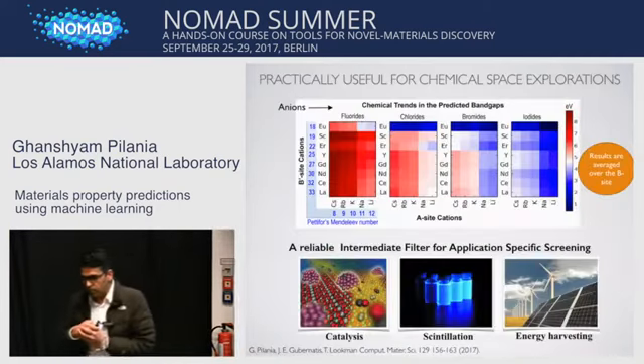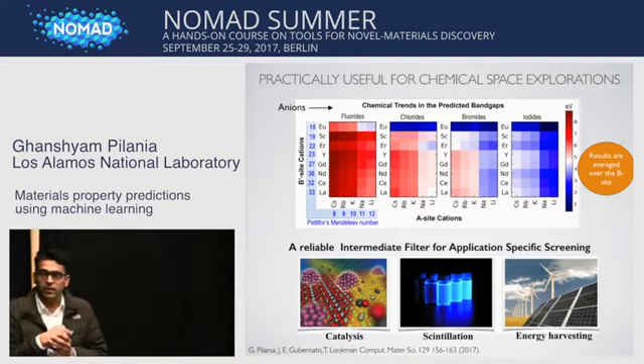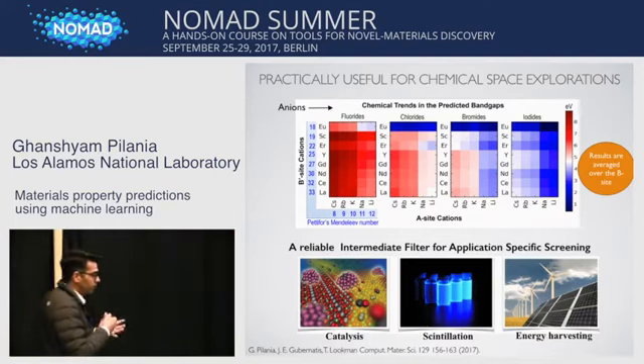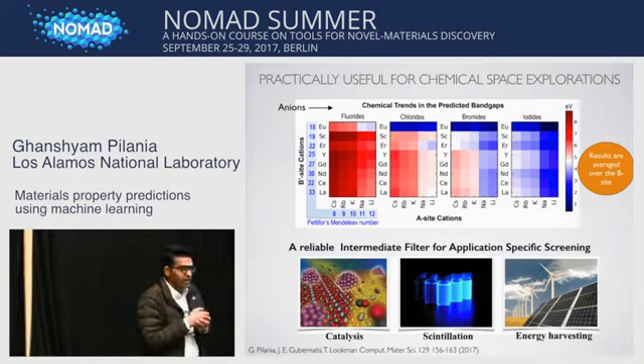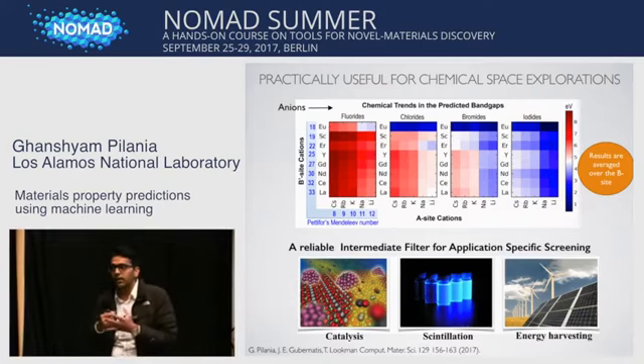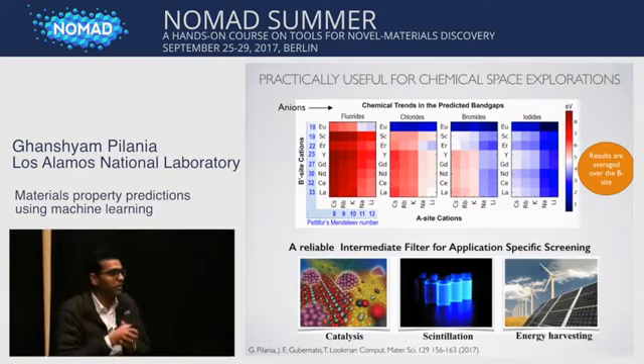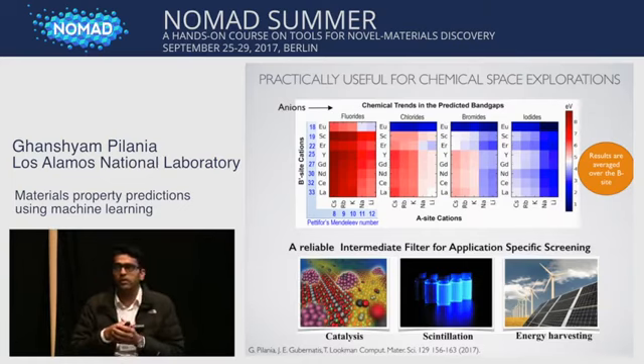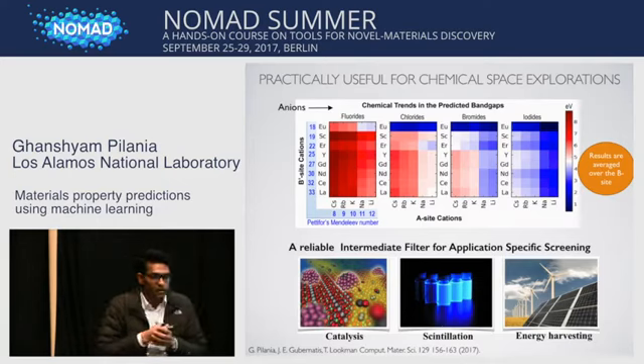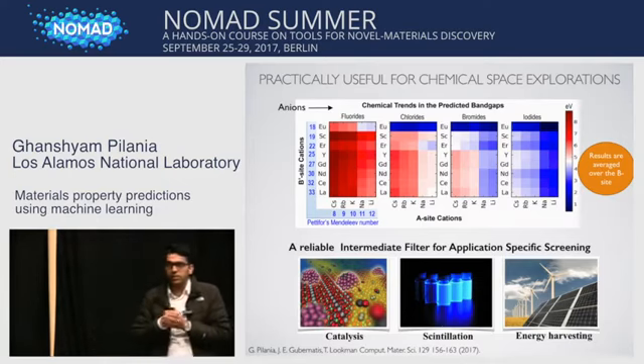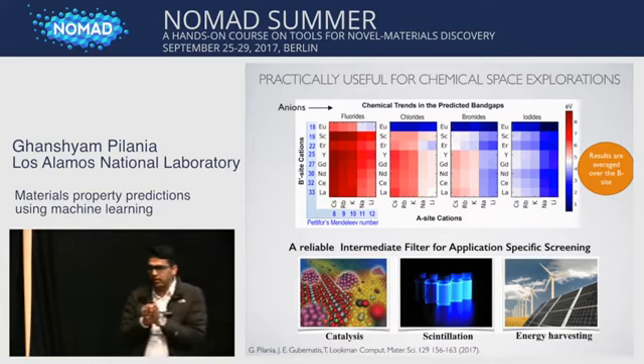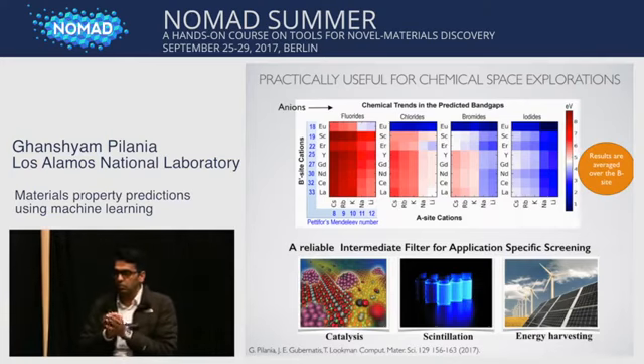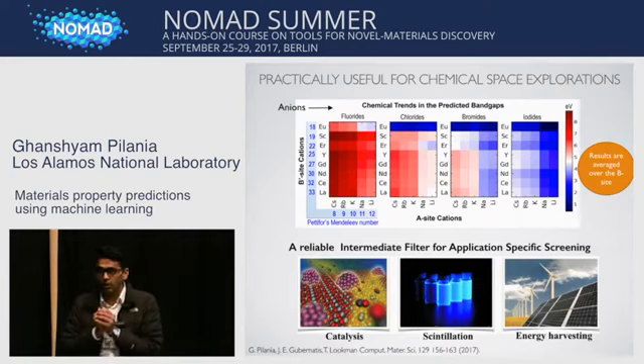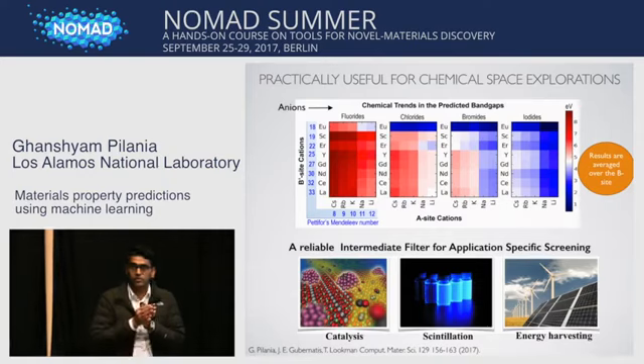So with that, we are at the end of the second example. I have showed you an example where we used PBE and HSE band gaps and trained a machine learning model to predict HSE band gaps for a set of perovskite compounds. I do need to mention that perovskite compounds are a special case in that most of them are cubic. So there are really no lattice distortions.